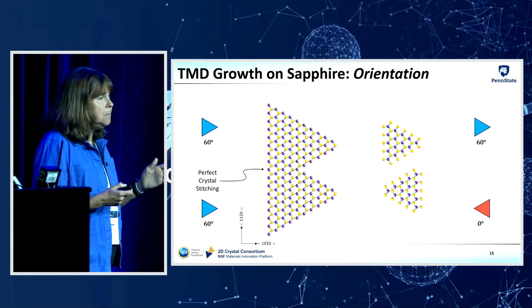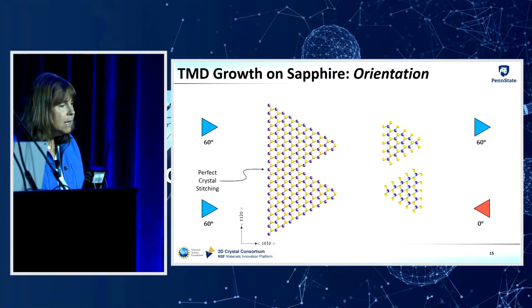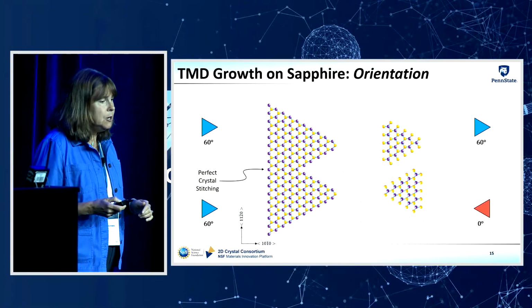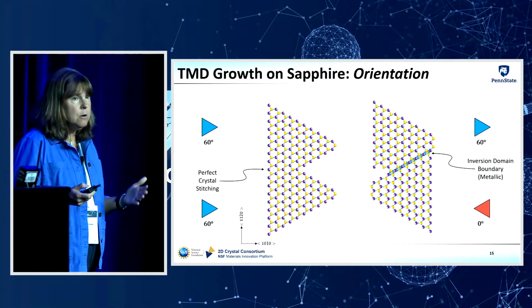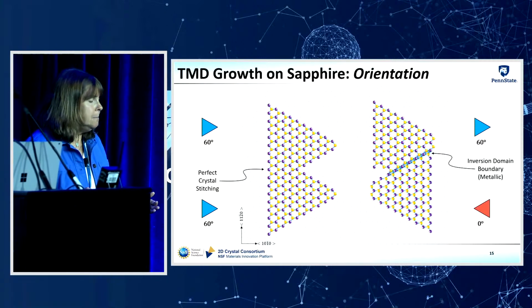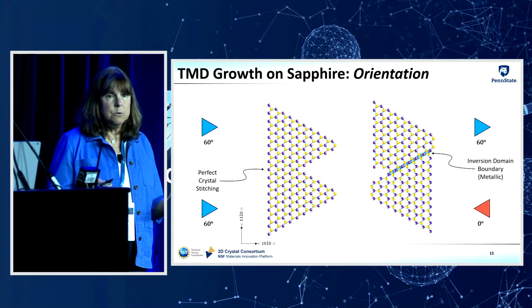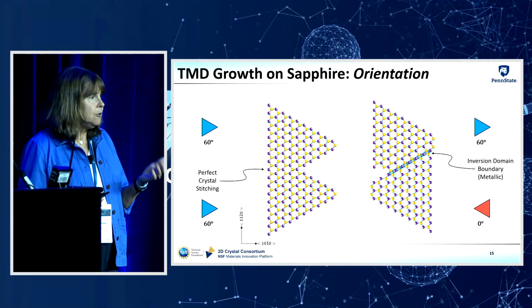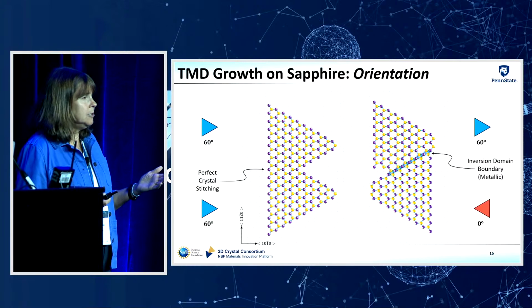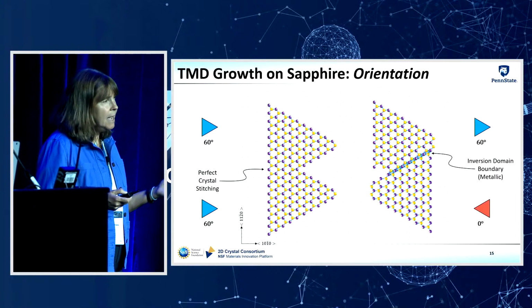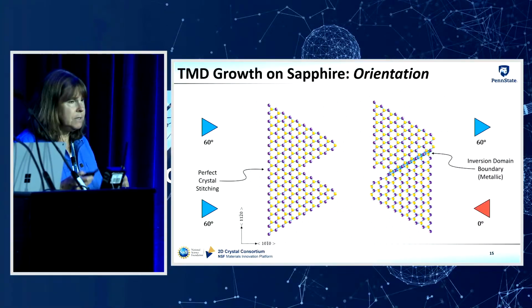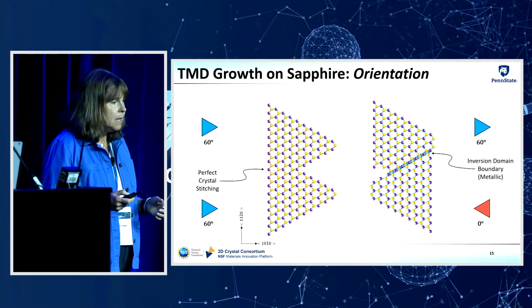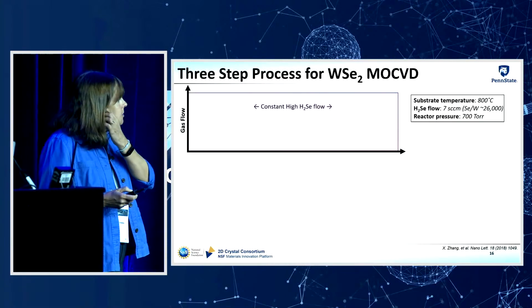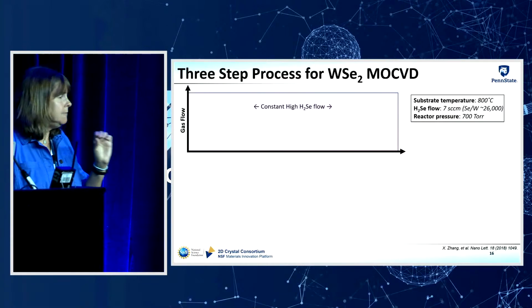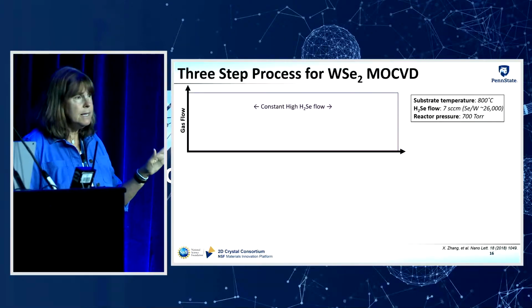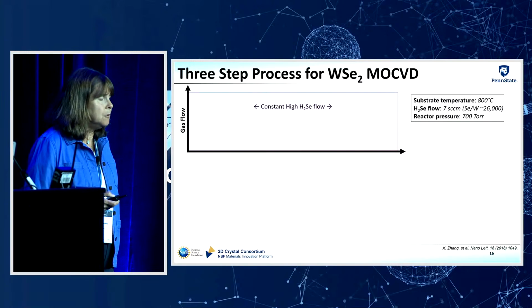And that's ideally what we want to have happen in our process. If we have oppositely oriented domains, whenever they grow and coalesce, they form an inversion domain boundary. It's also referred to as a twin boundary. This type of grain boundary has metallic character, so it introduces conducting paths into our semiconducting layer, which is generally undesirable. So our interest is to be able to control the orientation of our TMD domains so that we minimize the number of inversion domains that we're forming.